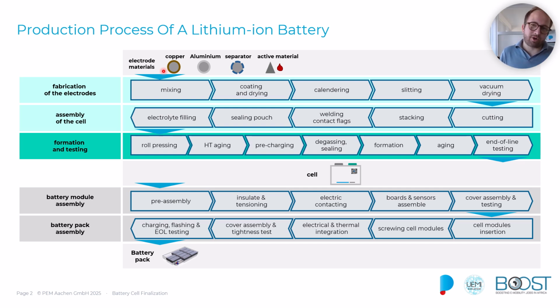I always compare it to a good wine, which also gets better over time and needs some kind of aging. Also, for some cell formats and chemistries, we need a degassing process. That means we often have gas forming inside of the cell during the formation and aging, and we don't want to leave that gas inside of the battery cell. So degassing removes those gases to avoid any swelling and ensure long-term stability of the battery cell. And that's done after the formation but before final sealing.